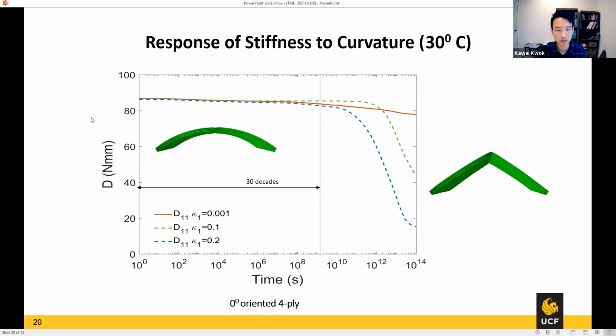The other response that we get from it is a localization response. We took a look at this unit cell model that we have and subjected it to a really high curvature over an extended period of time. We're trying to understand how, sometimes with this thin-ply composite, if you roll it around for some time, it suddenly snaps, breaks and fails. It does not fail as you fold it, so it's not at the elastic failure limit, but you just hold it for some time and it suddenly fails. So it's a sort of time-dependent failure.